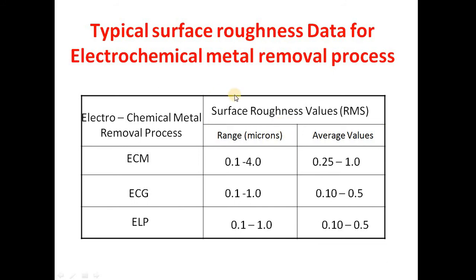So typical surface roughness data for electrochemical metal removal processes are in front of you. In the case of electrochemical metal removal processes, ECM or ECG or ELP, electrochemical machining or electrochemical grinding, these are different. In case of electrochemical machining, 0.1 to 4 microns range is possible for surface finish. But in electrochemical grinding, we get 0.1 to only 1 micron. Up to 1 micron we get the surface finish value. These are the cumulative average values of the same.